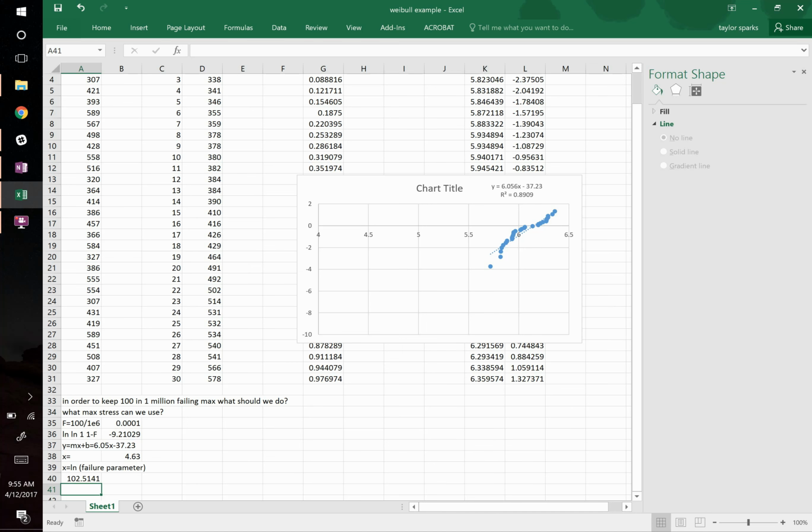If there's something about your process as you go from a small scale to a large scale that's inherently giving you a different type of flaw, like maybe, I don't know, knit lines from where it's pouring from a larger thing, it's a different mechanism of failure. So your Weibull analysis will not be applicable. But if you make it the exact same way, cast it the exact same way, you're just doing more of it, then odds are, the more volume, the better your odds of having that flaw. It statistically scales with it.